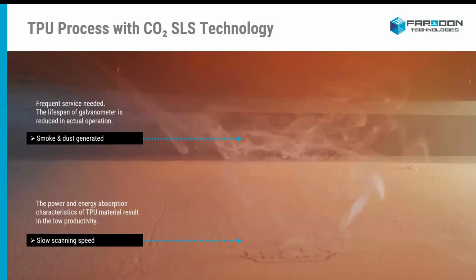So, looking at some material processability issues with CO2, traditional SLS technologies. One of the biggest obstacles to processing TPU with a CO2 laser is the amount of smoke and particulate that it produces during the sintering process. This smoke and off gas finds its way to the laser window, where it reduces laser power through the laser window at the part bed.